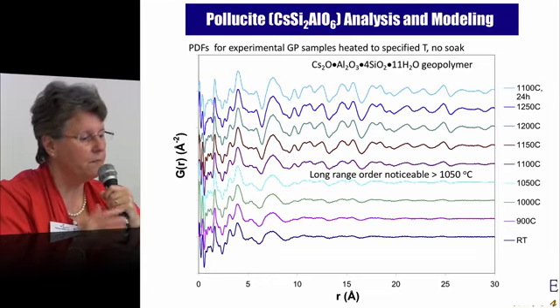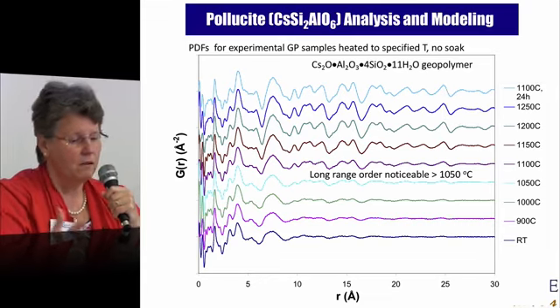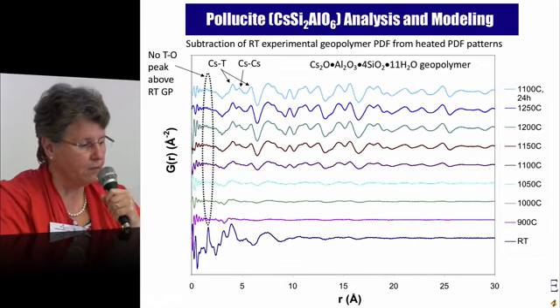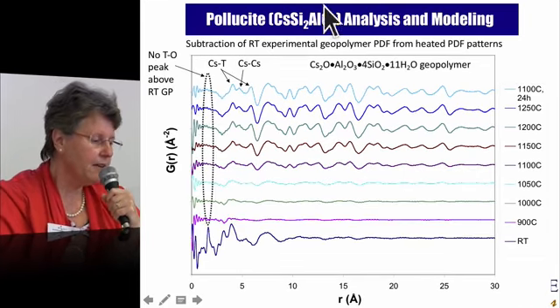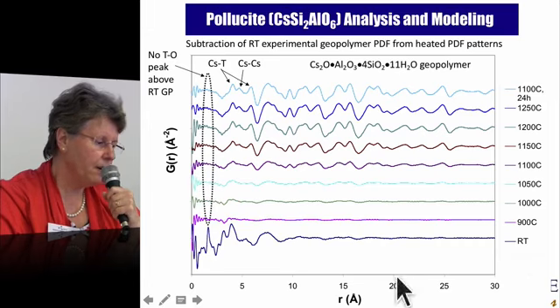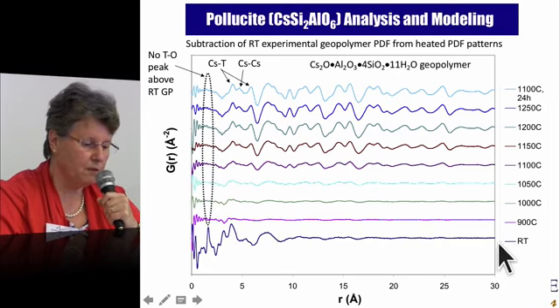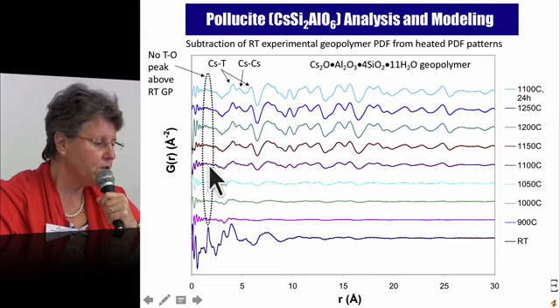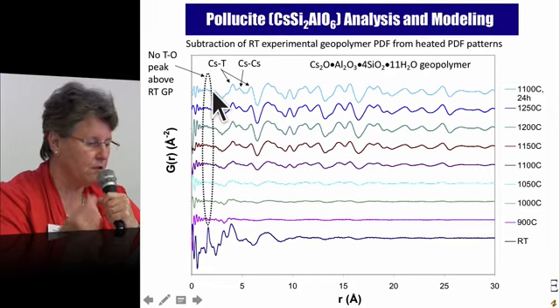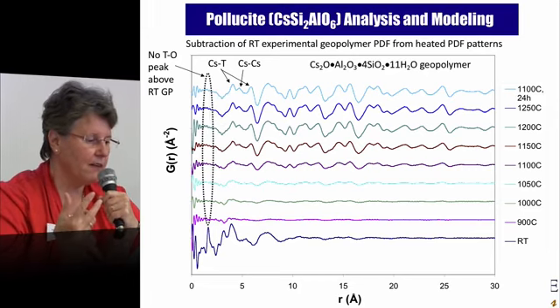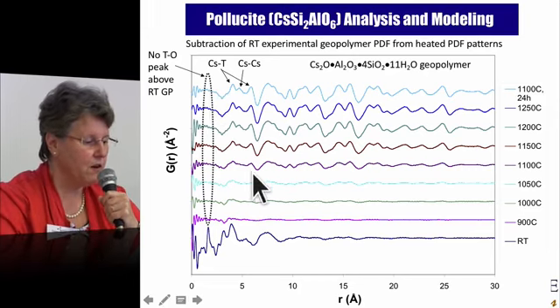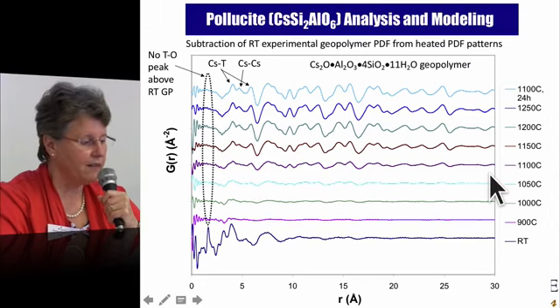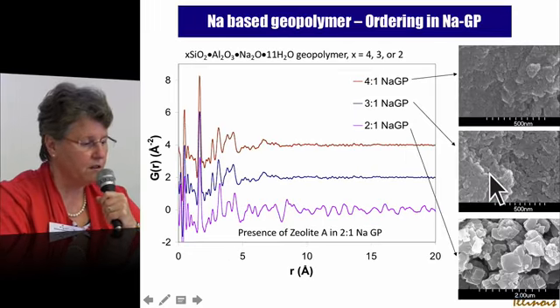So that might be useful like for radioactive cleanups. Now if you take that PDF function and you subtract the room temperature from the higher temperatures, there's no difference in the types of units, the SiO4 tetrahedra, the AlO4 minus tetrahedra. The only difference is around about 1000 it crystallizes.